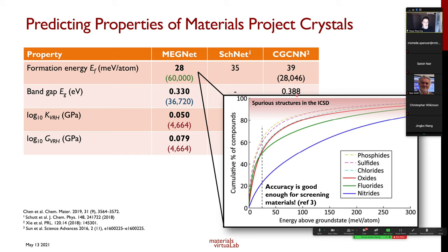You may wonder: is 28 meV/atom actually good enough? It is. Work by Sun et al. (2016) shows that about 80–90% of crystals in the inorganic crystal structure database — mostly already synthesized by experimentalists — have energy above the ground state of about 60–70 meV/atom. So 28 meV/atom is well within that threshold, meaning we can already make a good guess at whether a crystal is likely to be stable.